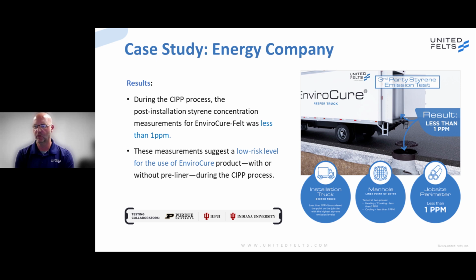million styrene was measured. The same goes with the cooling process. After cooling, less than 1 part per million styrene content was measured around the 5-foot incremental rings at the manholes. And at strategic places around the job site perimeter, less than 1 part per million styrene was measured.